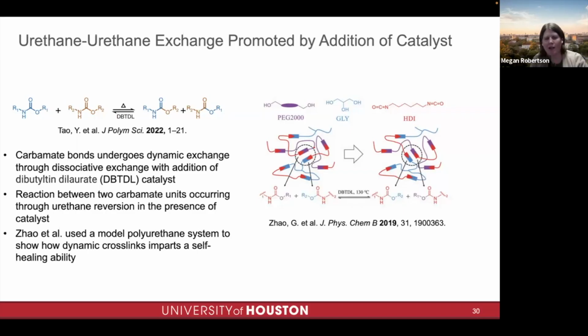One way to do that is a blocked isocyanate, where the isocyanate is blocked, meaning you add a functional group so it can't react with the hydroxyl groups on the polyurethane. Then we could mix at a certain temperature, and then later we heat to a higher temperature at which it unblocks, and then we can cure. We did actually implement that.